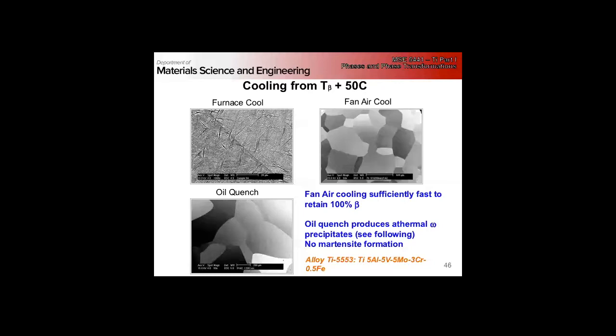If this were an alpha beta alloy and we did a slow furnace cool, what would our microstructure look like? Would it be a basket weave? Slow cooling of an alpha beta alloy, we'd have a well-defined colony structure with a completely covered prior beta grain boundaries with a thick layer of grain boundary alpha, right?